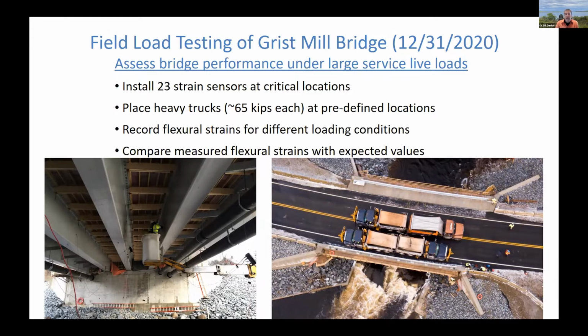We put a lot of weight on there. We put 4 overloaded dump trucks on there, about 65 kips each. We had, I think, in total, 262,000 pounds on the bridge, and they were put at predefined locations. And you can see from that aerial view on the lower right, for example, we're backing those trucks up together to get those heavy tandem axles as close as possible to midspan. We're moving them transversely across the bridge to load different girders more heavily. So a lot of thought goes into how we load the structure and where we place those trucks. What we're trying to do is maximize loads on individual girders to as great an extent as possible. And then we go take these flexural strains and compare them with expected values.